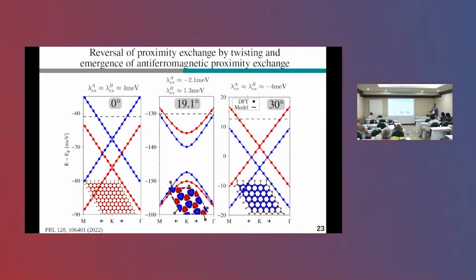Now if we go to the 0 degree case, we find exactly the opposite. This is really remarkable. Spin up Dirac states are pushed to lower energies, and if you calculate the spin polarization, it's again uniform but positive on the graphene. So you can essentially reverse the proximity exchange by twisting.